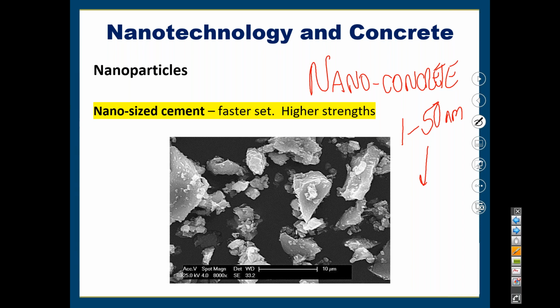So it's basically ground to a finer size. And just like the type 3, which is a finer, smaller particle than type 1, it leads to a faster set, higher strength. But when you get to the nano size, they have found that they've been able to create some concretes, and this is still being tested, but they've been able to do some lab tests where they found that they can get relatively the same strength or higher strength using even less cement. So overall, using less cement than you would if you were using typical Portland cement. So not only does it help you achieve the faster set, higher strength, but even if you get the same strength, if you're using less cement, that's both an economic advantage and also a sustainable advantage.